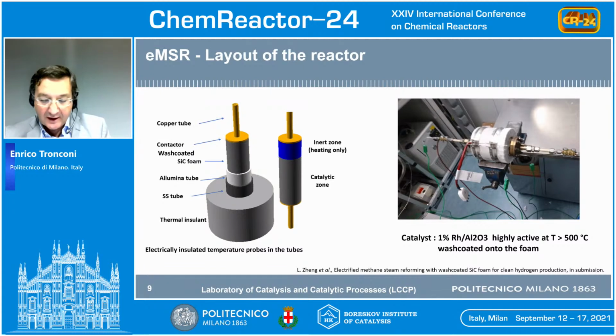So here we show the preliminary reactor layout that we have been using in our experimental investigation, starting from non-reactive heat transfer experiments. The system is based on a silicon carbide foam connected to a DC power generator, and the connectors are made with copper tubings welded to stainless steel plates with holes to enable the flow through. And the two plates are pressed onto high pore density copper foams to reduce the electrical contact resistance. And then we have the wash-coated foam, which is electrically insulated by a dense alumina tube and is placed inside a stainless steel tube acting as a pressure shell. Outside, we also have a thermal insulation layer. And we measure the temperature at the outlet of the foam by a thermocouple insulated by an alumina tube.